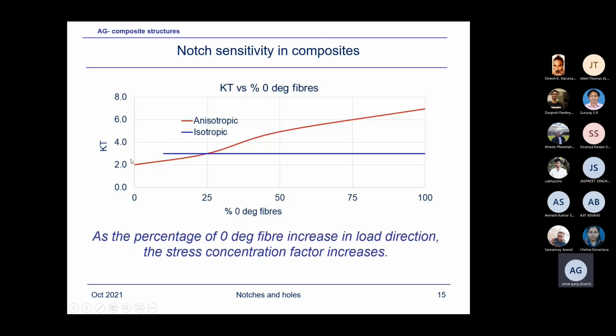Whereas if you have 0% zeros, or say, suppose you have only a plus minus 45 laminate, you will find the stress concentration factor of 2. So there's significant variation in the stress concentration factor depending upon the type of layup we have. It doesn't happen with the isotropic material. Isotropic material is always 3. And this behavior has implications on the failure or residual strength of the composite materials compared to the isotropic materials.